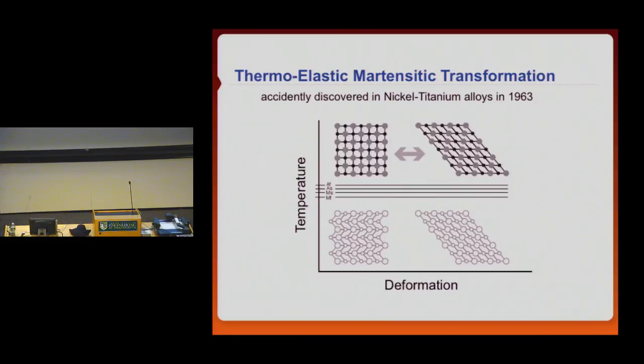that the effect in nickel titanium materials or nickel titanium alloys was found. And it was actually discovered at the Naval Ordnance Laboratory here in the United States, and that's why the material is also called Nitinol, N-I-T-I, and N-O-L for Naval Ordnance Laboratory. So they discovered this material when they tried to come up with a material for, I guess it was for submarines. It had to be high strength, corrosion resistant, and it had to be non-magnetic.